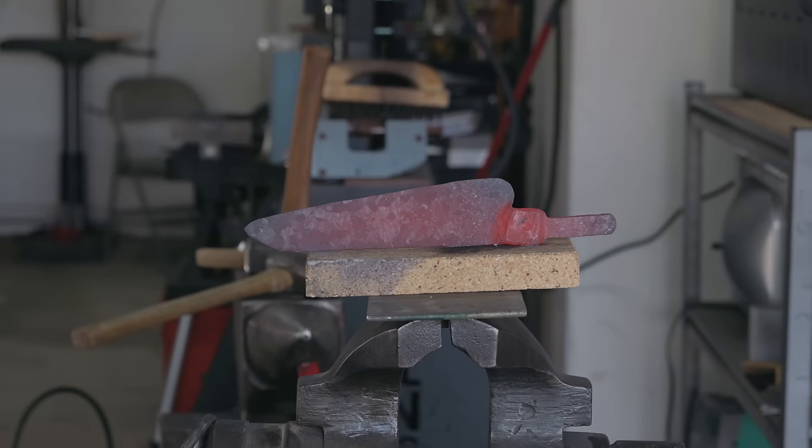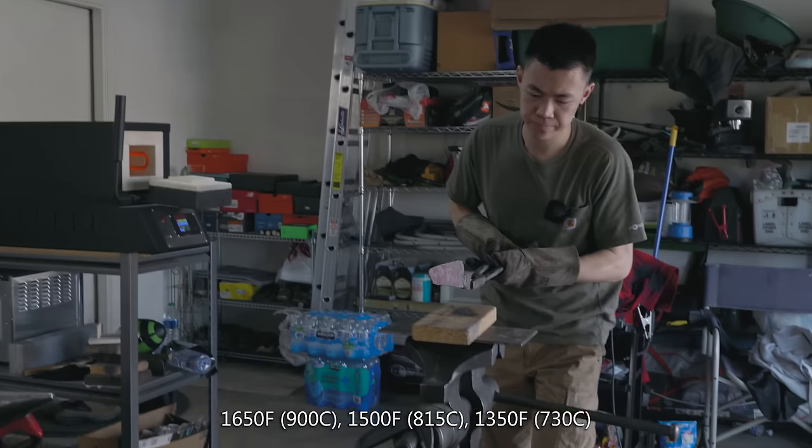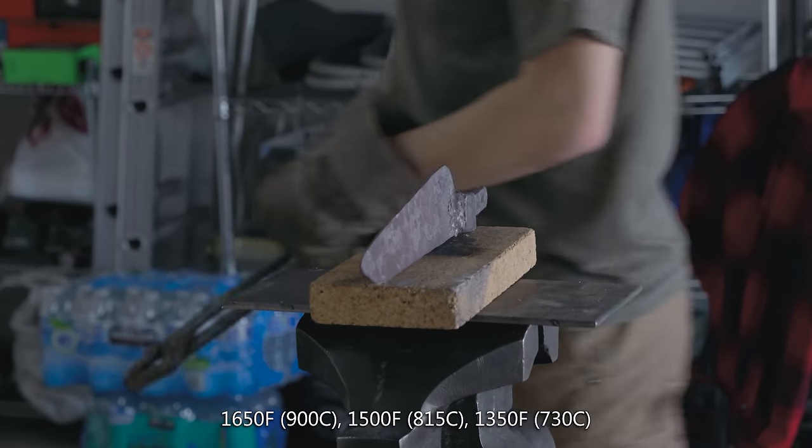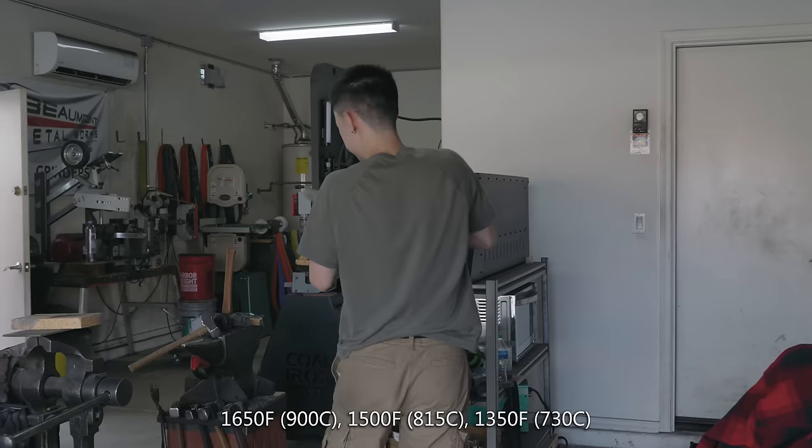I did three cycles of normalization for this blade, the first of which was at 1650 degrees Fahrenheit, the second was at 1500 degrees Fahrenheit, and the last one was at 1350 degrees Fahrenheit.